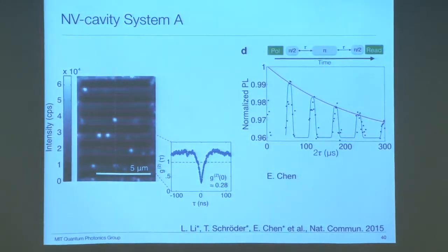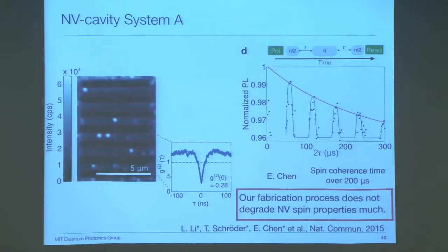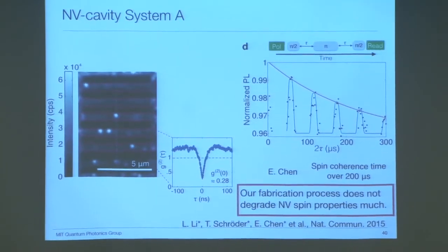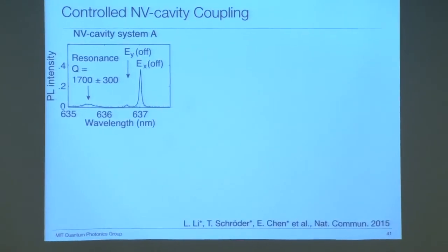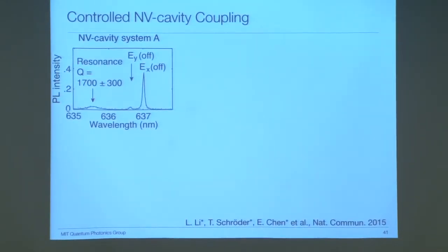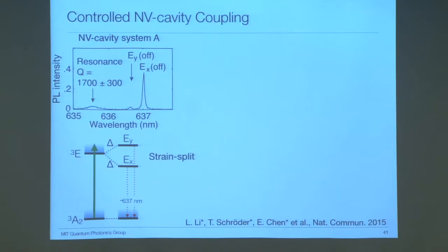The spin property of this NV center was also confirmed to be good. It was measured by my colleague Edward, and the spin coherence time is longer than 200 microseconds, which proves that our fabrication process does not degrade the NV spin properties much. For NV cavity system A, if we take a spectrum using a high-resolution spectrometer grating, we are able to see a cavity resonance with a quality factor of about 1700 and EX-EY transitions that are strain split by the internal stress inside of our sample to be the 2 ZPL transitions.